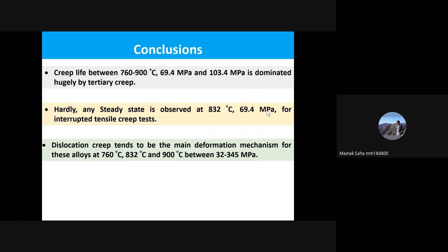Then thirdly, as I have discussed in one of the earlier slides, dislocation creep tends to be the main deformation mechanism for these alloys at these temperatures, 760, 832, and 900, and between 32 to 345 MPa, although the dislocation creep may be dislocation glide controlled or dislocation climb controlled. But definitely this creep mechanism was not at all discussed in the earlier work. Okay, and this is a very new work. It's going to be totally in a new direction. It's not at all discussed in the major work, and in all the other subsequent works on gamma TiAl.